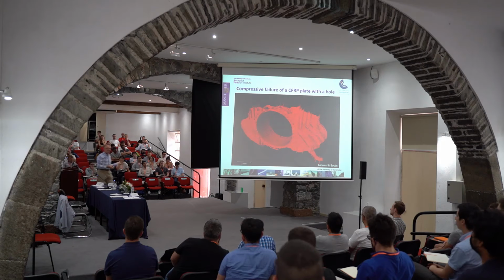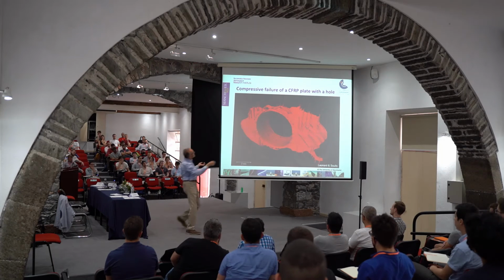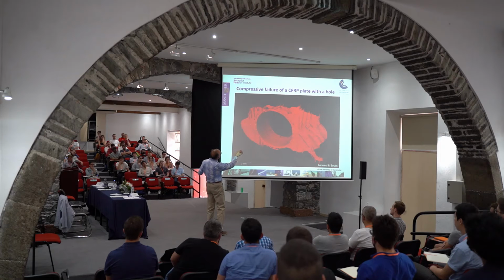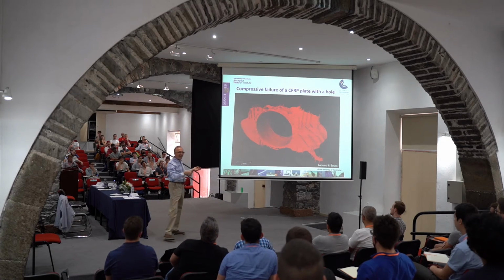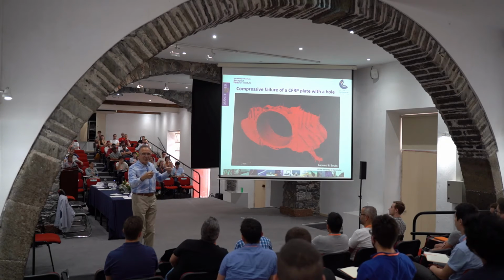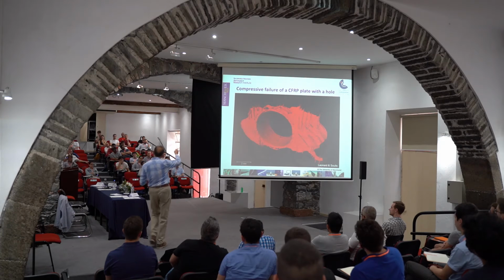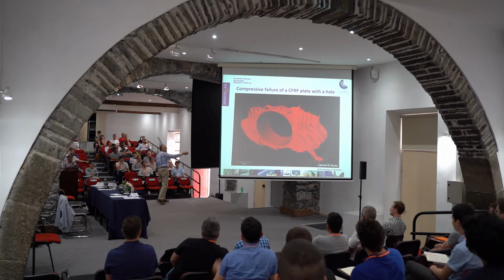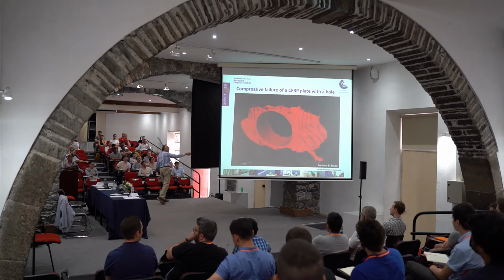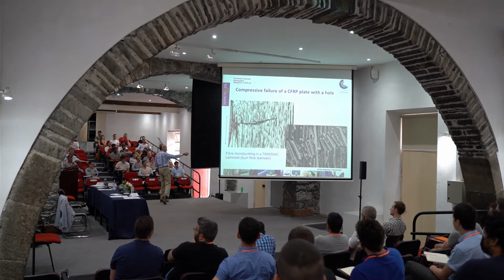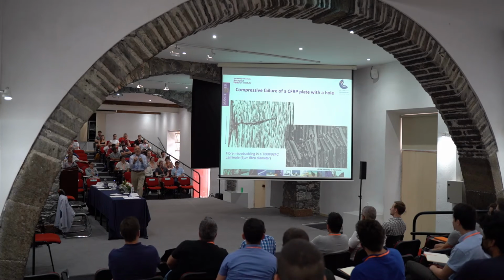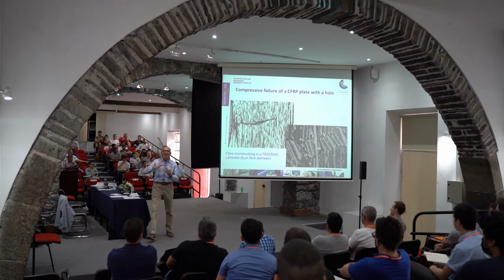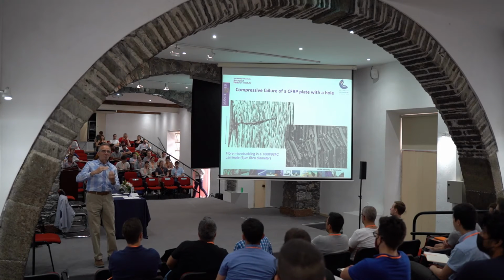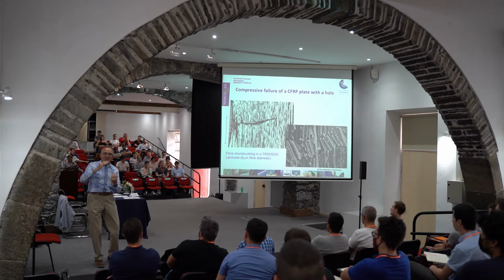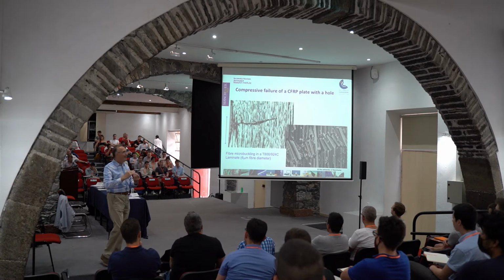And if someone has a very experienced eye, they're going to see that somewhere here there is already fiber microbuckling. That crack goes transverse to the applied stress and propagates across. Yes, I had shown that already. I'm repeating now. Can you see? There you go. That's the crack. What I did there is I removed ply by ply. I have removed the off-axis layers, very carefully, to expose the zero plies. And this is the crack.